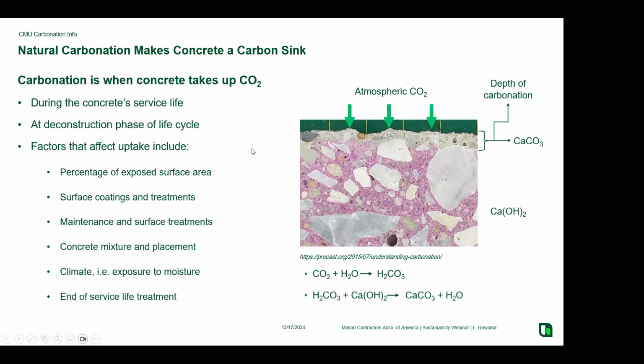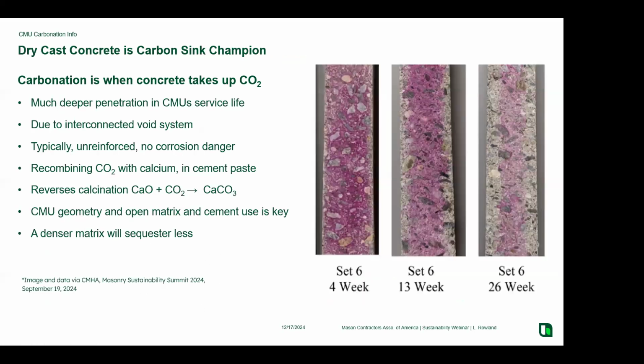Concrete gains weight. Masonry blocks gain weight as they absorb this CO2, believe it or not. The process you can see here is you've got CO2 plus some water, which can be water vapor, produce carbonic acid, which combines with calcium hydroxide, and essentially you're forming new limestone, right? So it is a natural phenomenon that's going to happen whether you try to make it happen or not. This is part of what happens with all concrete, and in block, it's a really big factor for us because of the exposed surface area associated with the block, and of course any treatments and the different applications. Because the geometry of the block is such that it leaves a lot of voided spaces and openings, you get a tremendous amount of carbonation. You get this natural sequestration of the